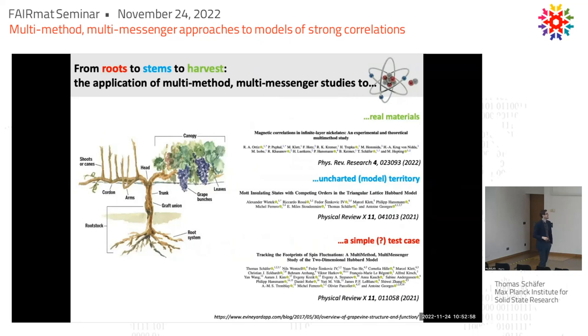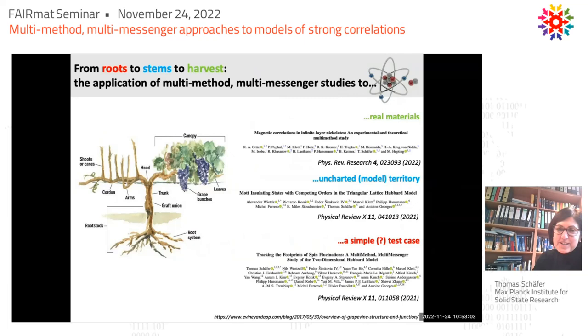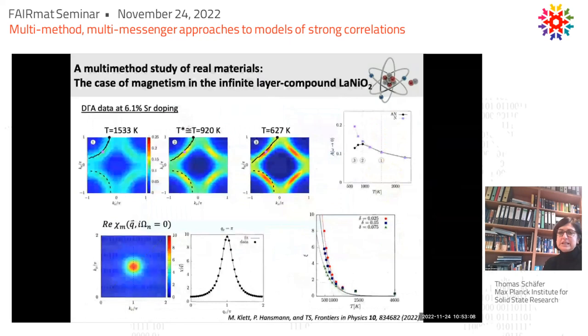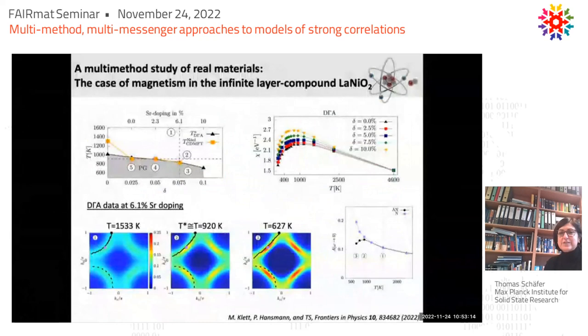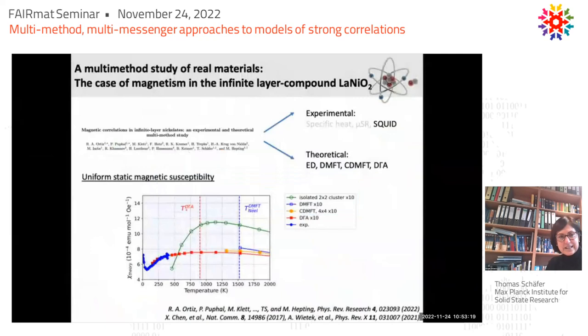Thanks. Roger? Yes, I have a question on the nickelates. You are showing us a very good agreement, for instance, for the uniform static susceptibility, but you have these factors of 10 or factors of 3. When I look at these susceptibility measurements, they look rather what you would expect for these materials. It's not that the nickelates are behaving very differently from the rest of the materials with this type of structure. So my question is, is the fact that you are getting this behavior because your model is rather general, and this is the type of behavior you would expect for these materials? Now it's a question of the parameters to get the scaling in the right region. Is it something like that?